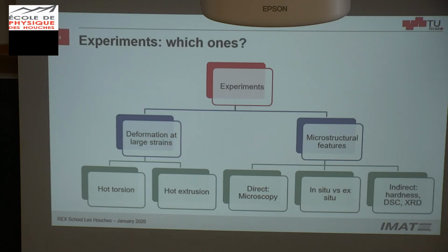And which experiments? For deformation at large strains, you don't have many experiments. You have hot torsion. This is a typical experiment. It's not a new one. You may have something in the industry, similar, like hot extrusion or something like this. You are going to show something about max strains, which is also a way of getting large strains, but in small steps. So you get a strain, then you have static phenomena, then a strain again, a static phenomena, strain again, a static phenomena. So you have a cumulative large strain, but not continuously.